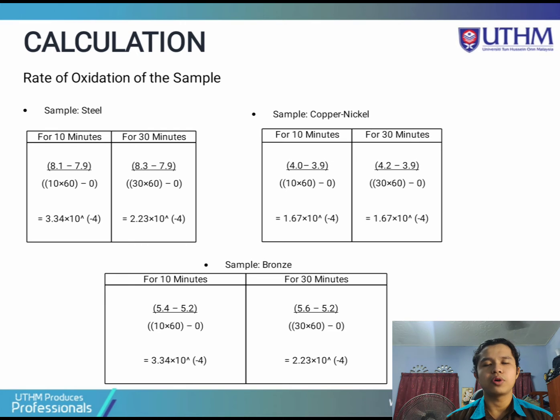For the sample bronze, for the duration of 10 minutes, 5.4 minus 5.2 over 10 times 60 minus 0 equals 3.34 exponent negative 4 gram per second. For the 30 minutes duration, for the bronze sample, 5.6 minus 5.2 over 30 times 60 minus 0 equals 2.23 exponent negative 4 gram per second.